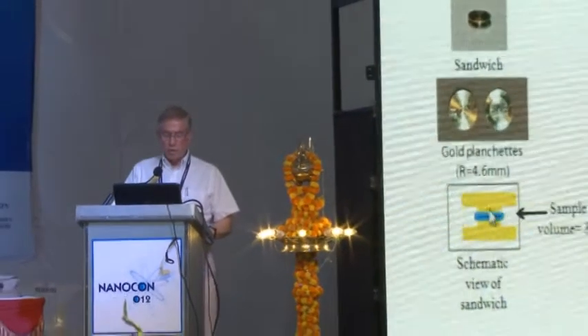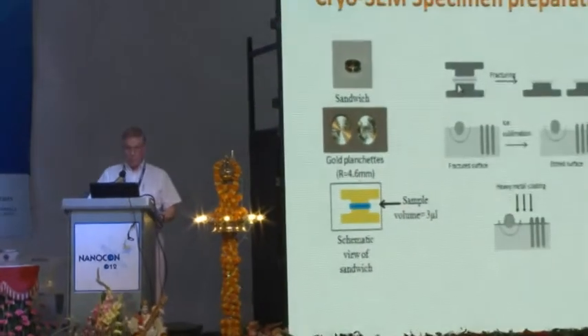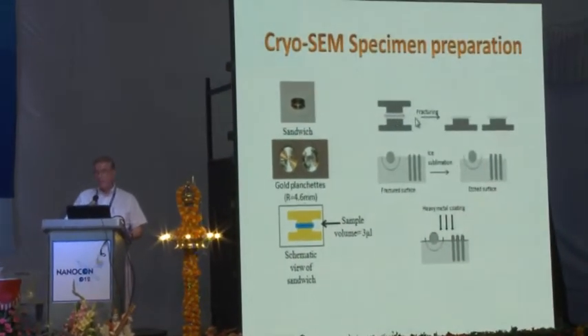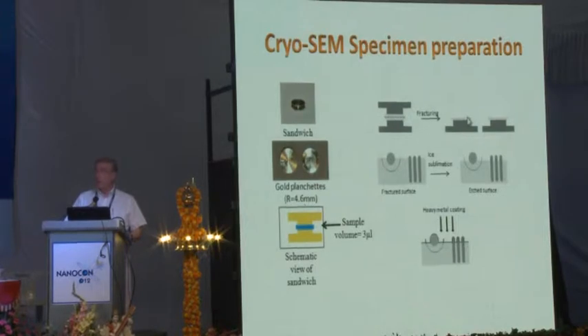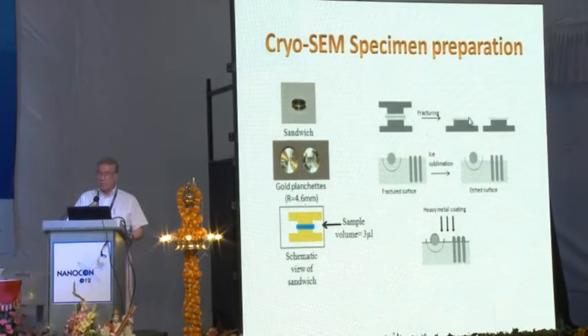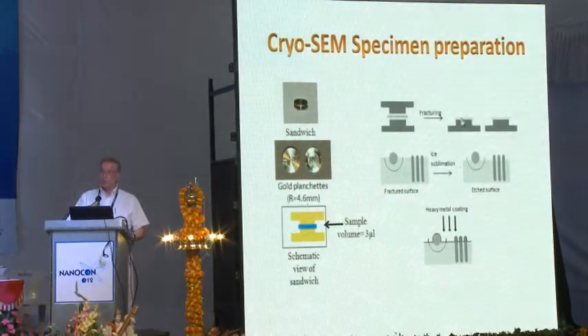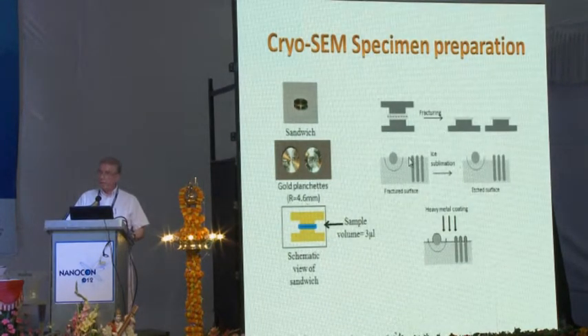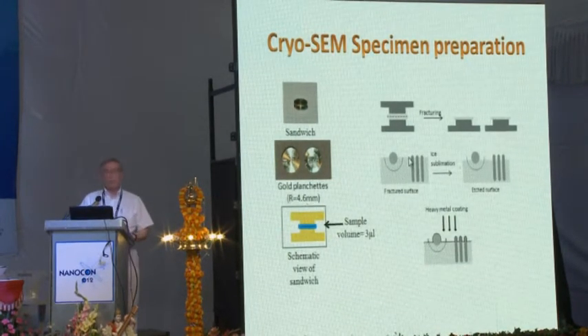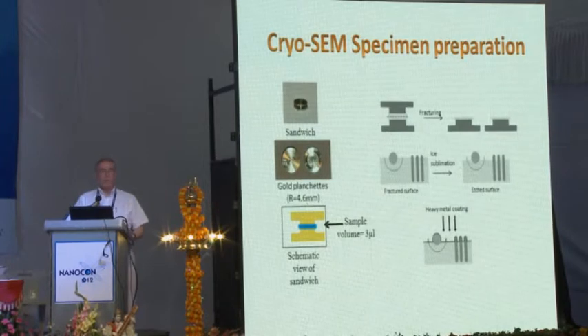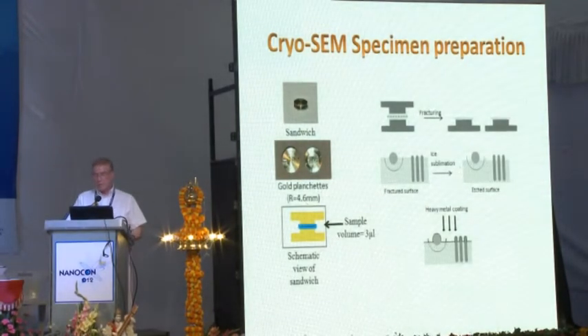fracture it. Here's one example. What you see here is a sandwich made of these two gold planchettes. This is a schematic. You have a liquid, a few micrometers of liquid between the two. You plunge it into the cryogen, and you open it. You open the sandwich. By opening the sandwich, you get two fracture surfaces. And then, if you want, you can sublime some of the volatiles in order to get better topographical contrast.